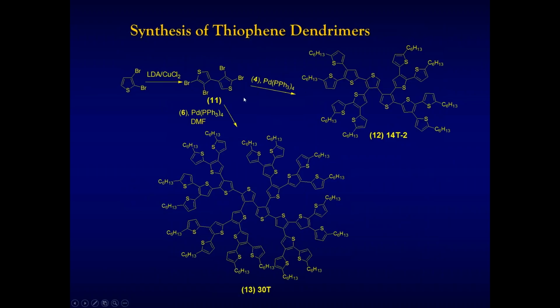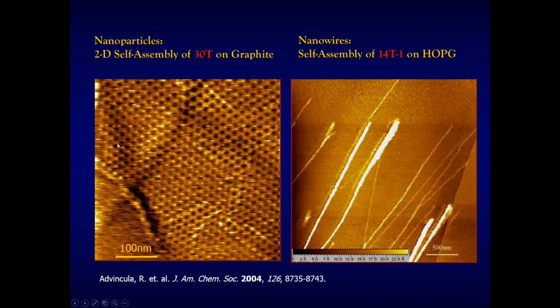So we have synthesized, in this case, polythiophene dendrons or dendrimers using a convergent approach through metal-mediated reactions such as Kumada coupling or Stille coupling. As you can see here, we can utilize an AB2 monomer, which is a basic unit for dendrimer synthesis, where the thiophene has two bromo groups, alpha and beta, and then you have a hydrogen, a proton group, which makes it susceptible to lithiation reactions. So with this design, we can then grow the dendrimer by basically growing branches of, let's say, 3T.